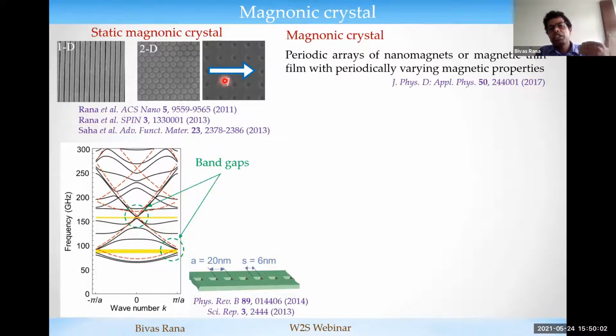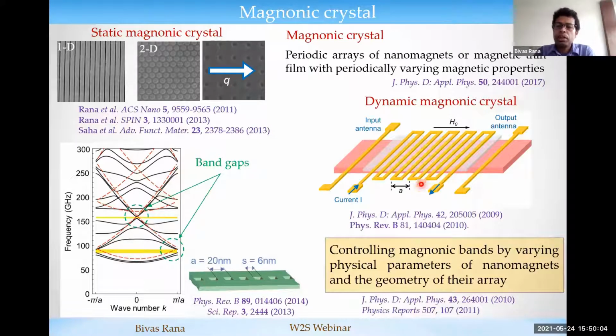So you can also create a dynamic magnonic crystal. One nice example is this one. You make a meander shaped conductor on top of a ferromagnetic waveguide, then you send a charge current, and that generates a spatially non-uniform but periodic magnetic field. So the effective field is periodic here. In this way you can make a dynamic magnonic crystal. Just by changing the value of the current, you can change the magnonic band structure in a very nice manner.